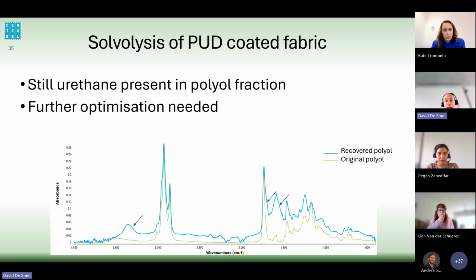We already did some trials, and we can see that we can degrade the PU coating. We can also recover purely the polyester fabric, but if we just focus on the PU coating, then we can still see with infrared analysis that the degradation of the polyurethane is not complete. So we can still see some urethane peaks, which are indicated here by the arrows. Above 3000, you can see a small urethane peak, but also a shoulder around 1700, which is the carbonyl of the urethane. You can also see a little bit of the CN amide stretching just above 1500. Again, it's really a shoulder, so it is not high percentages, but it's not complete. There's still an estimation of about 10 to 20% urethane peaks present. So we need to further optimize the chemical recycling process.